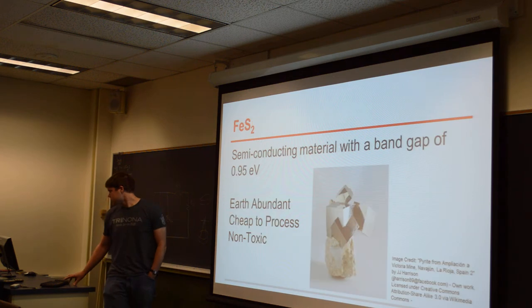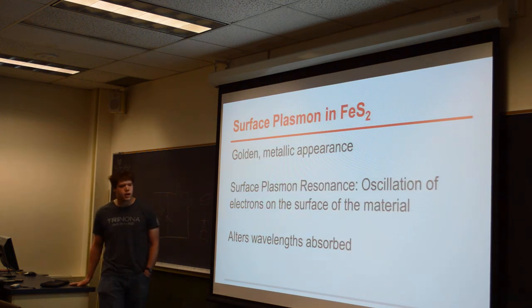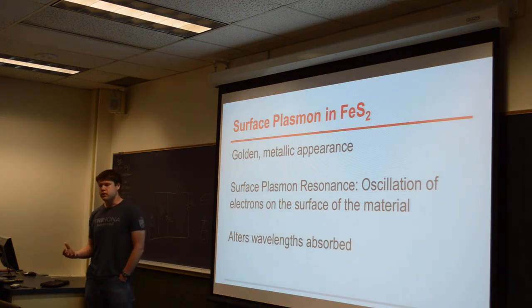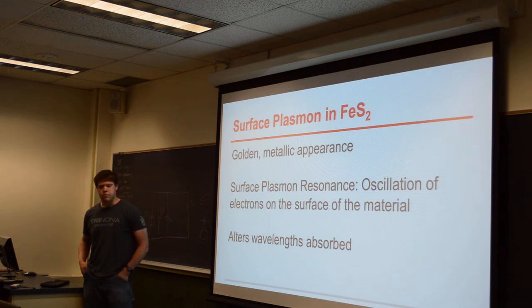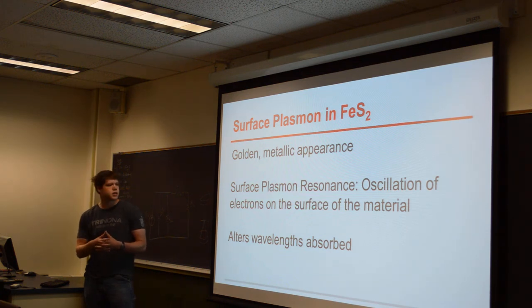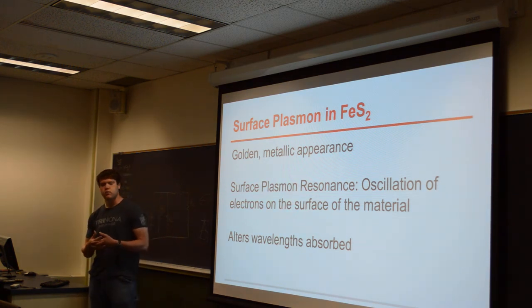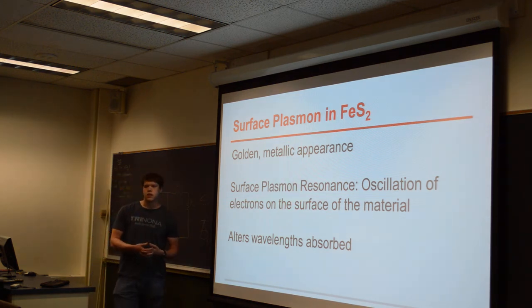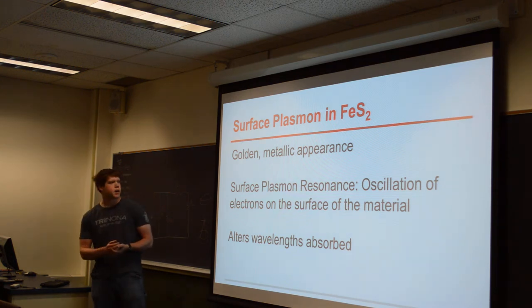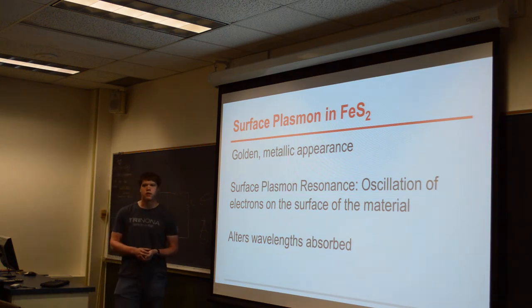As you can see from this picture, it has this metallic appearance, and that's probably caused by the surface plasmon resonance. What that is, is basically charge carriers mostly associated with sulfur vacancies in the material. As light is absorbed in the material, it oscillates these charge carriers in a coherent wave. As far as using this in a solar cell, it changes the wavelengths that are absorbed and effectively reduces the band gap energy in this material to the point where it really couldn't be used effectively or efficiently in solar cells.